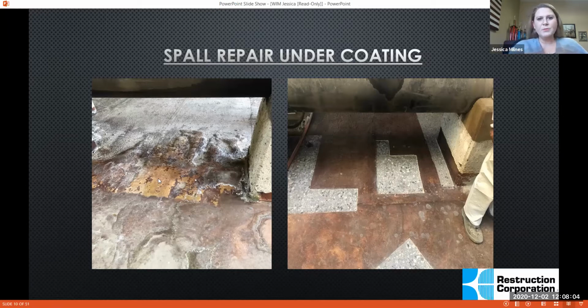So what we do is we go in and we remove the coating and we take out any of the bad concrete. And then we want to use really, really sharp edges, squares, anything like that. We don't just lob it. The reason behind that is in a durable repair like this, we want to have good exposed sides so that the new material that we put in is going to bond well and have a cohesive coating at the end.